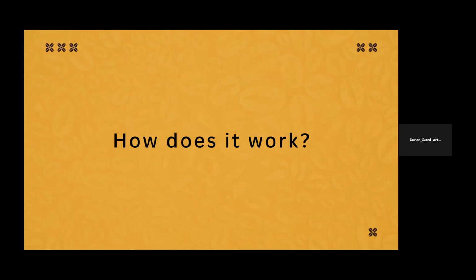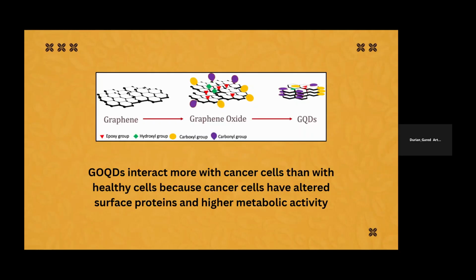Then, how does it work? The answer lies in their structure and chemistry. These particles are extremely small, about 20 nanometers, and carry oxygen-rich groups such as hydroxyl and carboxyl. These groups interact more strongly with cancer cells than with healthy cells, because cancer cells have altered surface proteins and higher metabolic activity. Moreover, cancer cells live in an acidic environment and produce more copper ions and reactive oxygen species, or ROS, which makes them ideal targets for GOQDs. In short, GOQDs naturally prefer cancer cells, and when they bind, they produce fluorescence, or glow, making cancer detectable.